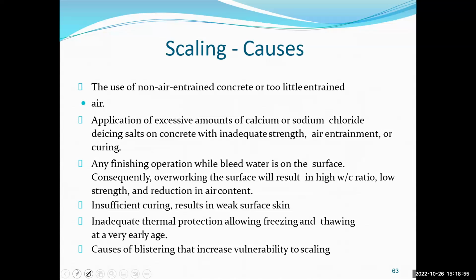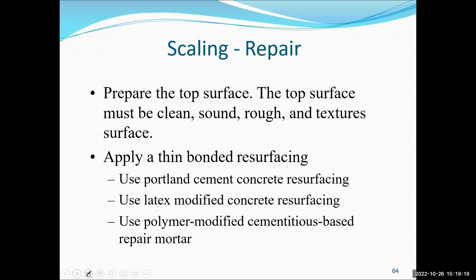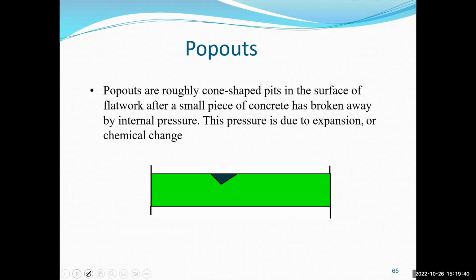The causes of scaling: using non-air-entraining agent, because the air-entraining agent absorbs the water pressure in the concrete; an excessive amount of calcium or sodium chloride; finishing while the bleeding water is still on the surface; insufficient curing; and inadequate thermal protection. These are what cause the scaling. To repair it, of course, you clean the surface and apply a bonding layer, which could be Portland cement, latex-modified concrete resurfacing, or polymer-modified cementitious material.